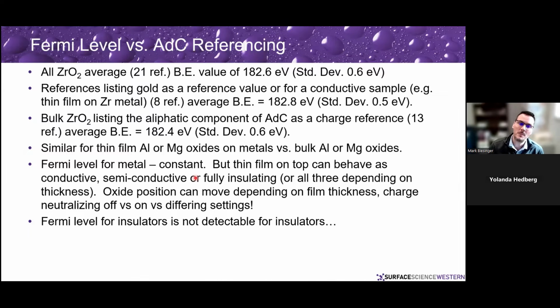If I look at the bulk zirconium oxide listing the aliphatic component of AdC as a charge reference, we get a binding energy of 182.4 eV. So now you can see how these are two different references based on what kind of samples you have. We can do similar things. Aluminum's one that really sticks out like a sore thumb. Thin film aluminum oxide versus bulk oxide.